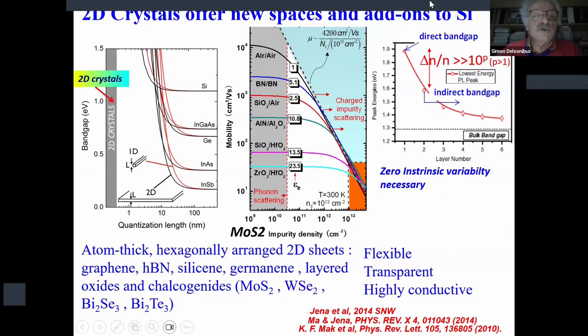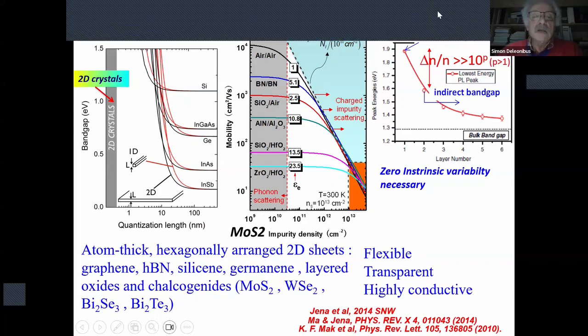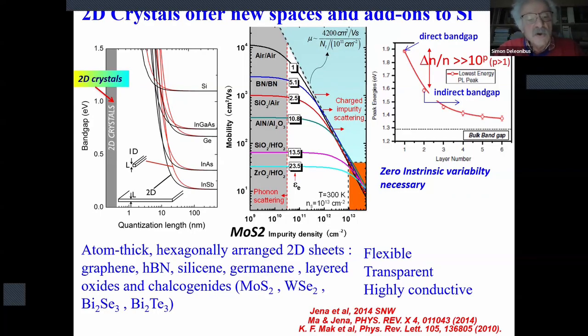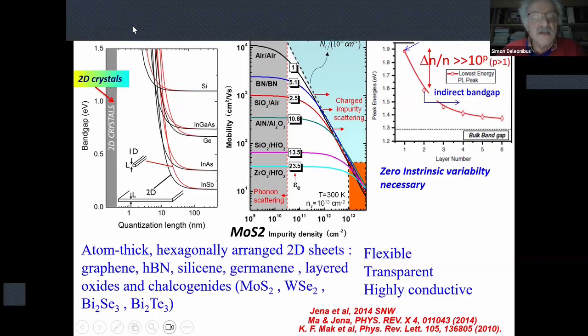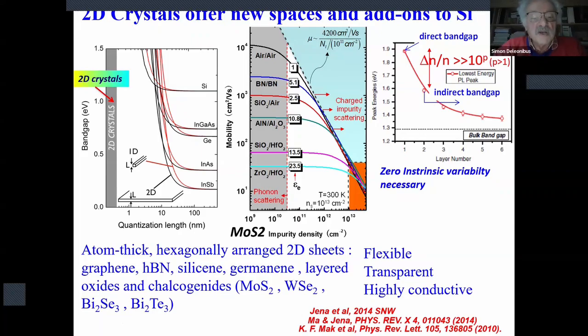Okay, so here I mentioned the 2D crystals regarding the scaling of transistors. So here you can see on the left-hand side that scaling the film thickness, or what we would call a quantization length, increases the band gap if you evolve from 3D semiconductors to 2D or 1D semiconductors. So, well, it's a dramatic situation for III-Vs, and for silicon, it's a little bit better. However, reaching very small dimensions really poses a problem. 2D crystals make sense, namely 1 atomic sheet as a thickness.